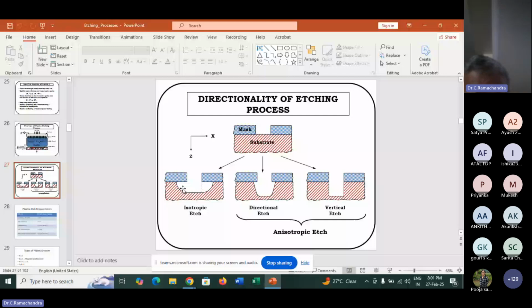In the case of wet etch, we always get an isotropic etch. But in the case of plasma etch, I can get an isotropic etch, somewhat directional etch, or a perfect vertical etch, by selecting, tuning and optimizing process parameters. Therefore, controlling process parameters becomes very challenging and very interesting for developing different profiles. These profiles depend on my process requirements.